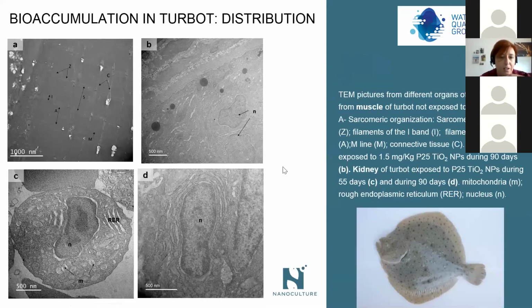Then for turbot, so far we analyze muscle, kidney, liver, and intestine. Here you can see several transmission electron images of tissues not exposed. This is muscle, this is intestine, and you can see here kidney that were exposed to titanium dioxide nanoparticles. And we cannot see nanoparticles, so there is no big significant accumulation that we can report by electron microscopy. But what we can see is that there are some effects, such as this enlargement of the endoplasmic reticulum. So we think that there are some effects in some of the tissues of the turbot.